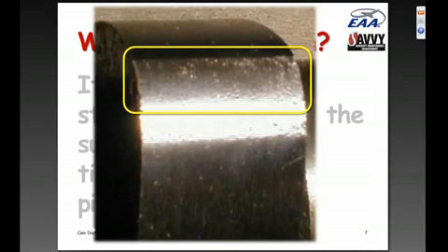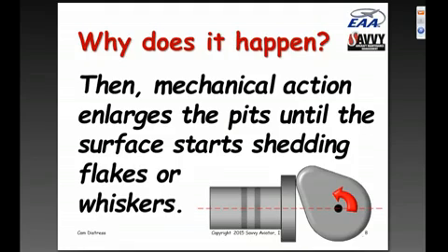Then once these pits develop on the surface due to disuse and corrosion, when the engine goes back into service and the airplane is flown, the mechanical action of the cam rubbing against the lifter face will start enlarging those microscopic pits until they get big enough that the surface starts shedding significant size pieces of material, typically in the form of flakes or whiskers. We'll take a look at some of the metal that is liberated when this spalling process happens.